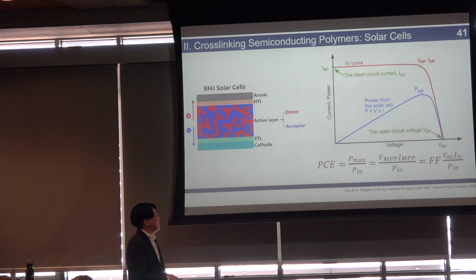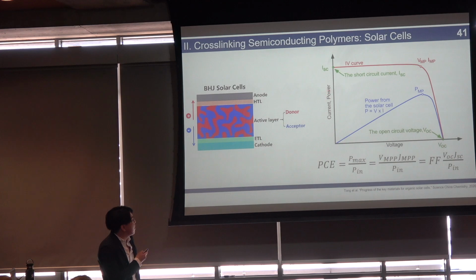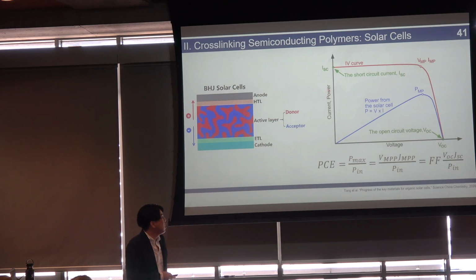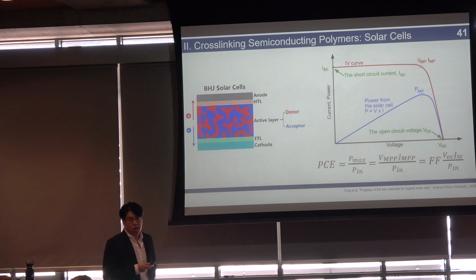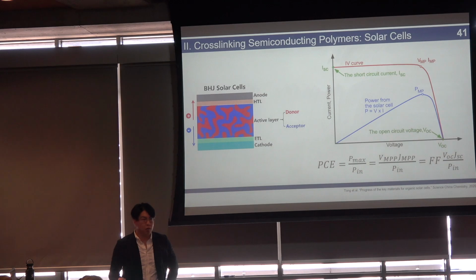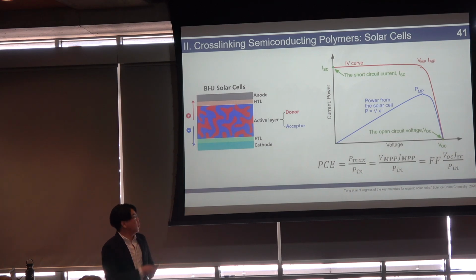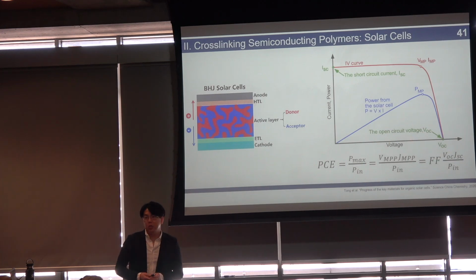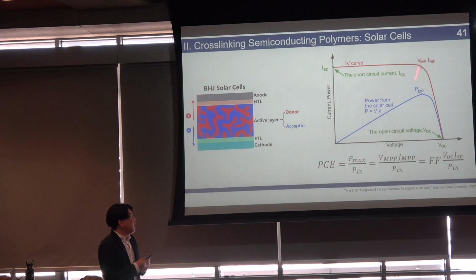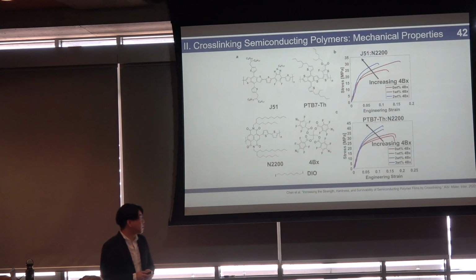And we can characterize these solar cells with something called an IV curve. We can measure the current the device outputs at any given voltage, and from here we can extract the short circuit current, which is how many photons we're able to absorb. We're able to extract the open circuit voltage, the max voltage, and we're able to extract the fill factor, which is basically how square this red line looks. And in terms of efficiency, we could do some basic math, and we can calculate what our maximum power is, and we could divide that by the power that we input, sunlight, and we get a total power conversion efficiency.